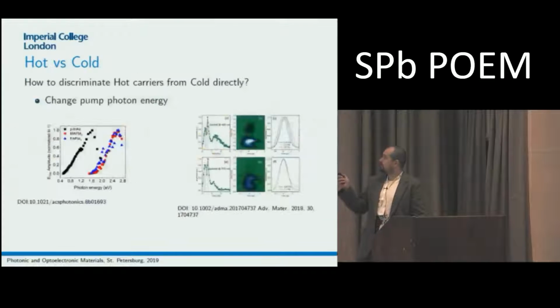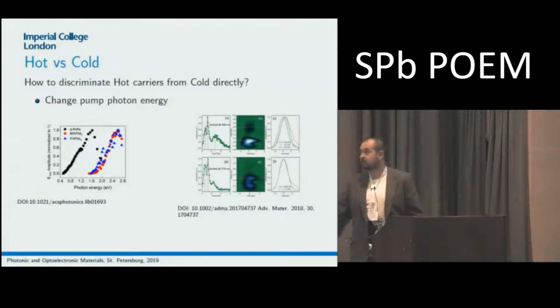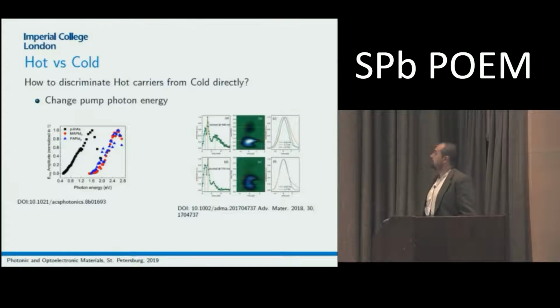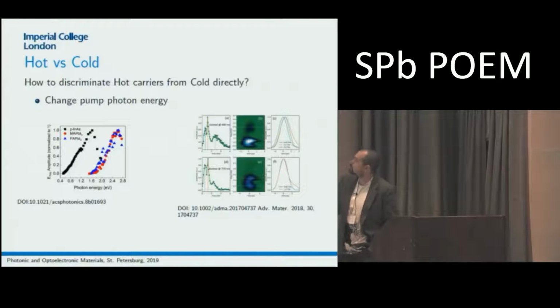And then just a short flashback to the previous talk. These are the results for terahertz emission spectroscopy, I think this was MAPI as well. This was not the first demonstration, but the second, but they managed to publish it faster, I guess. What they have shown is that they excite just above the MAPI band gap with 770 nanometers, and in the terahertz spectrum they have generation mostly below 2 terahertz.